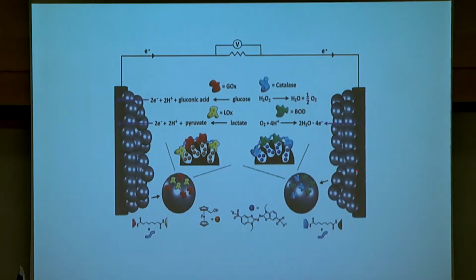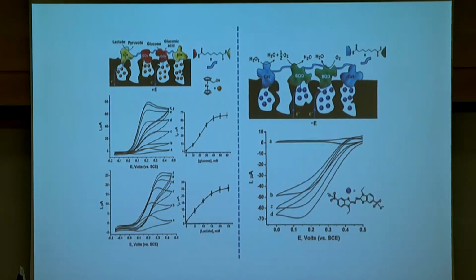And as a cathode, we applied the bilirubin oxidase, and we were able to introduce this ABTS electron mediator into the pores of the nanoparticles in order to get an electrocatalytic electrode for oxygen reduction. So we have here the possibility to make a biofuel cell with lactic acid, and with glucose as fuel a second biofuel cell, or alternatively to take glucose and lactate as fuel products, and these are abundant materials, to generate electrical power. And this is exactly what we did.